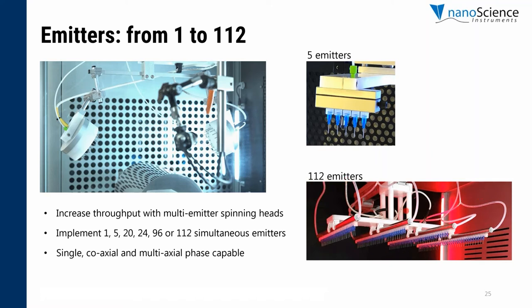This is also in single phase, but then we can go and operate through a coaxial arrangement. We can even use a solvent gas jacket, meaning that we can add a solvent surrounding the needle tip, and this is to improve the electrospinning process and even avoid clogging from happening. So if that interests you for your application needs, we can also work around that.